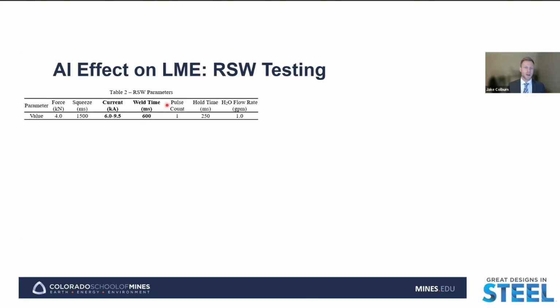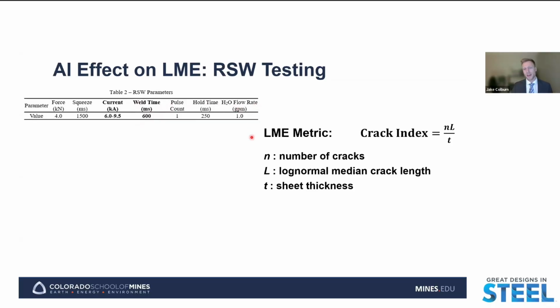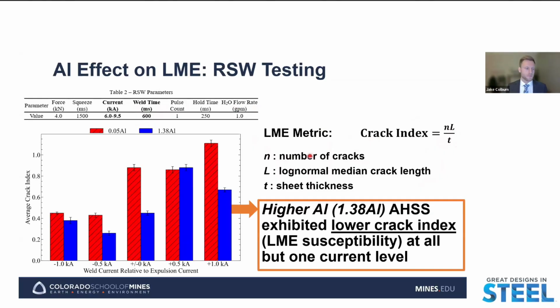And we did that to ensure that there's adequate heat input to initiate LME at each of the weld conditions that we used. And so the LME metric that we're interested in using here is the crack index, which is going to be the product of the number of the cracks and the log normal median crack length for a given sheet thickness. And so we see that a higher crack index is going to be indicative of a higher LME susceptibility because there's either a greater number of cracks and/or a greater average length of those LME cracks. And so here's the figure on the left.